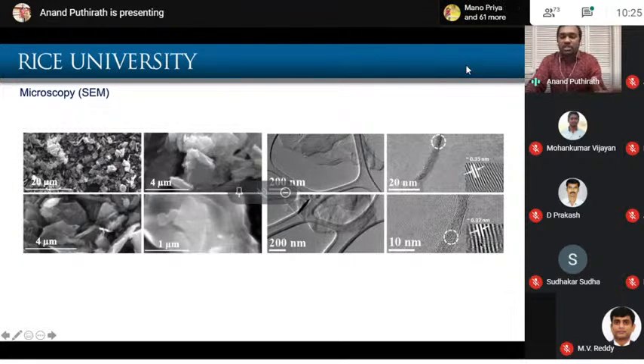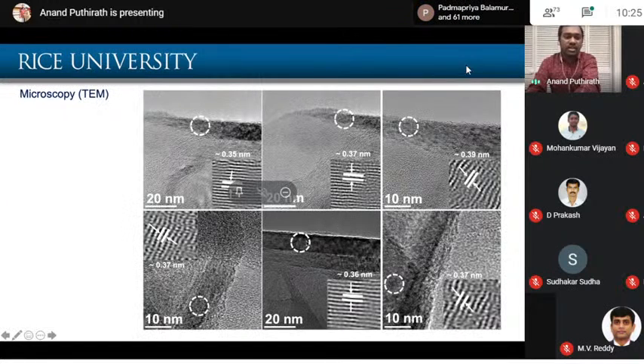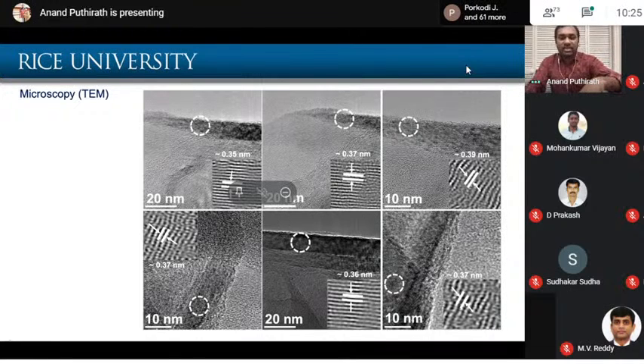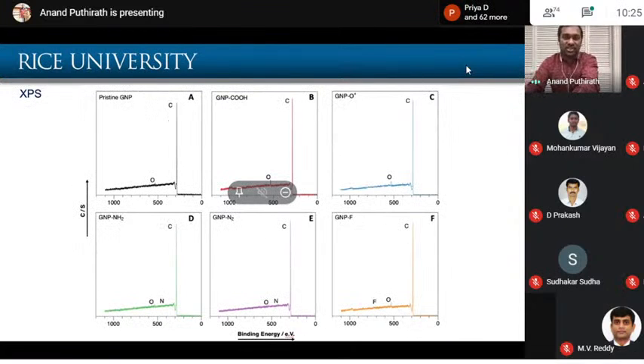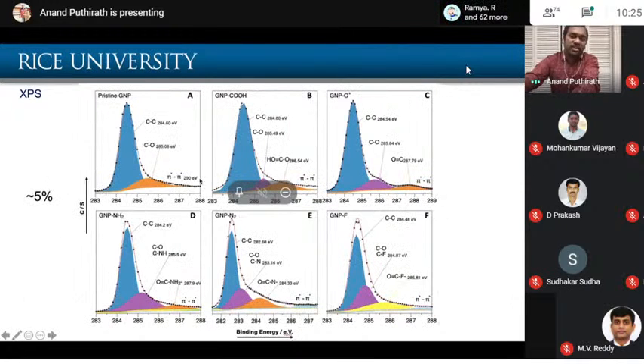They are sp2 hybridized and bonded to each other, and you can see the d-spacing between the layers, which is around 0.37 nanometer in the case of graphene. Here you have multi-layer graphene, right? Graphene nanoplatelets, and we have to make sure that we gently functionalize the system, and we look at the electron microscopy of all these functionalized systems, and they are still keeping that particular d-spacing. So which means the treatment we have done is not harsh enough to destroy the whole structure.